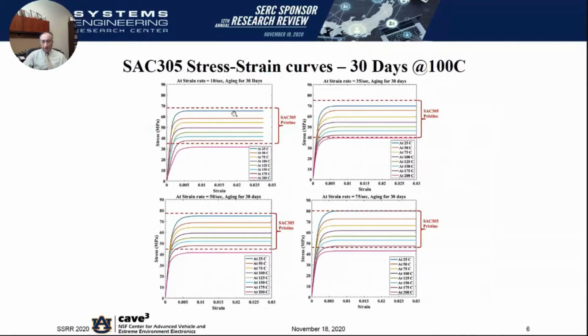The data has been acquired at a bunch of different temperatures. So here we are looking at data from 25 to 200 degrees centigrade. And what you notice is as the operating temperature increases, the ultimate tensile strength of the material actually successively drops. The elastic modulus changes as well.